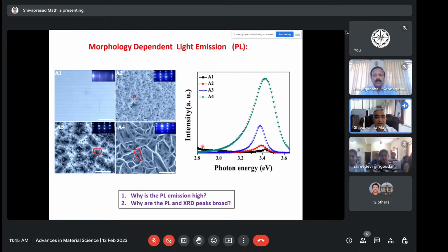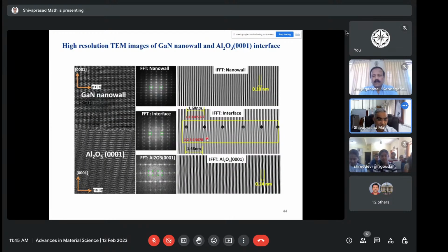So we looked at it under a high resolution microscope, and we saw that the defects were very few in these materials. You can see here at the interface that the defects terminated very easily. And also because of the strain in these nanomaterials, the defects can go to the edge, and in the main material there will be no defects, so they can become very efficient. And also because of the angle.